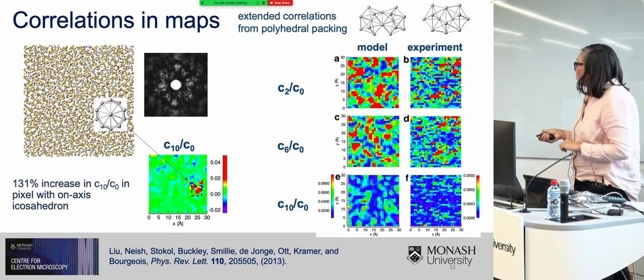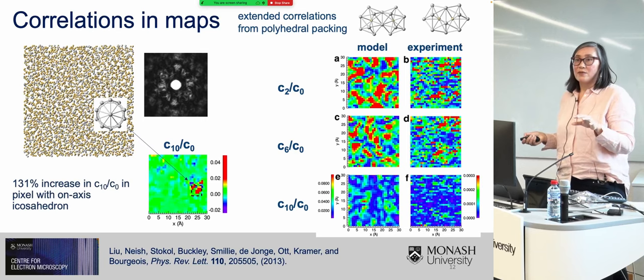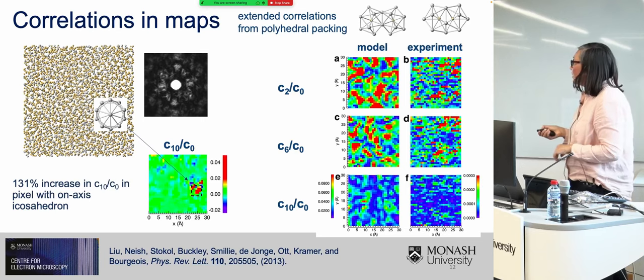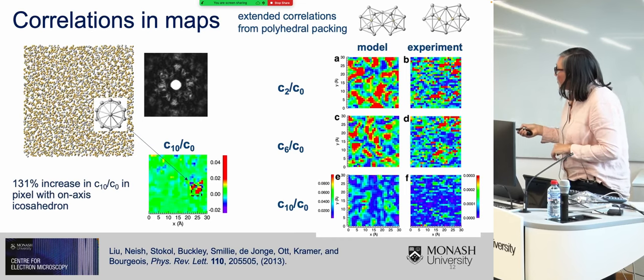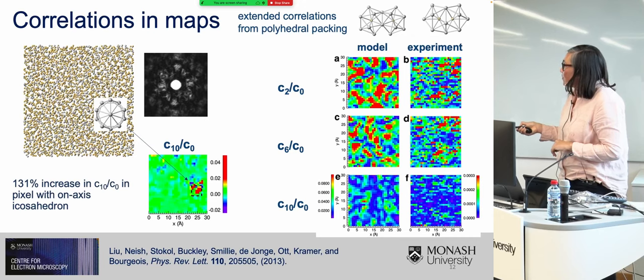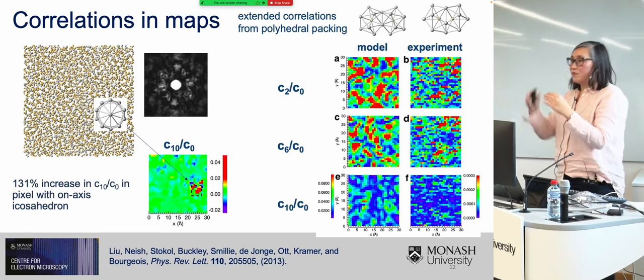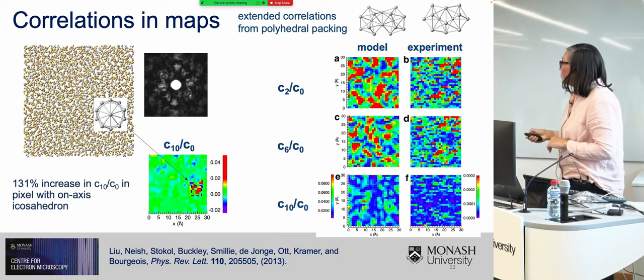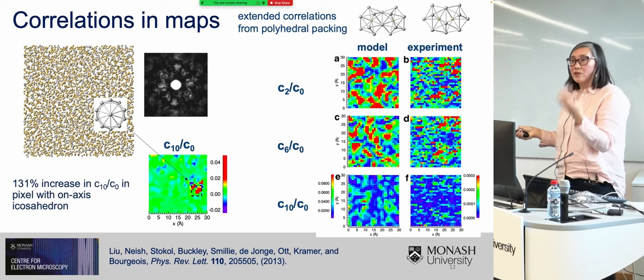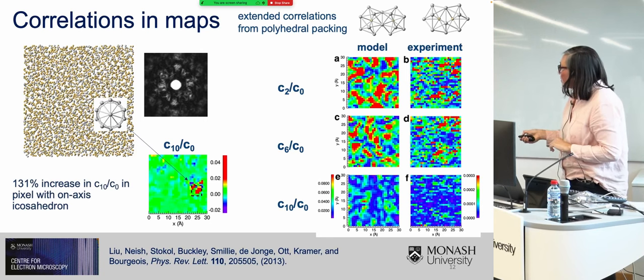Initially I set out to prove that these were indeed sensitive to very local order within my glass. You can see here I've simulated an electron nano diffraction pattern of an icosahedron looking down its tenfold axis of symmetry on top of a very large slab of a metallic glass. Even though you can't really tell that there's this prominent tenfold symmetry in your diffraction pattern, if you calculate the angular autocorrelation and map out the n equals 10 Fourier coefficient, you see a very, very strong elevation in the tenfold symmetry in the region where the polyhedron is.